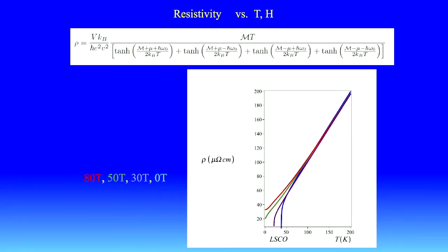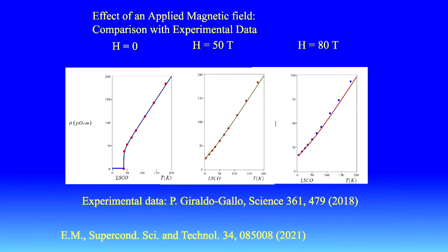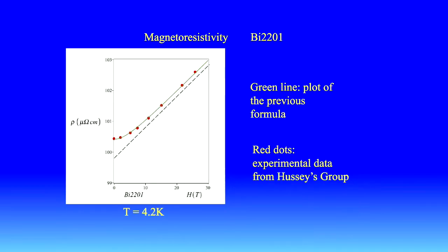And then we have the distortion of the superconducting gap as we go from 0 Tesla here, 30 Tesla, 50 Tesla, and 80 Tesla. So you see that the gap is destroyed. The experimental data are from this paper. And this is a nice result also from Hussey group. Magnetoresistivity. This is resistivity versus magnetic field. You see that we have a very good agreement. This is for bismuth 2201.